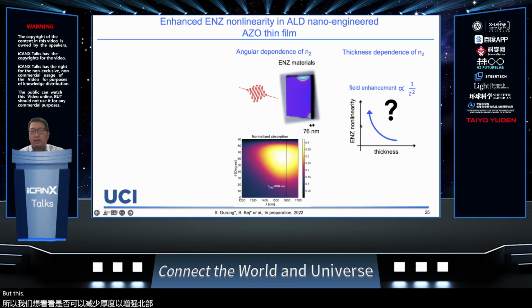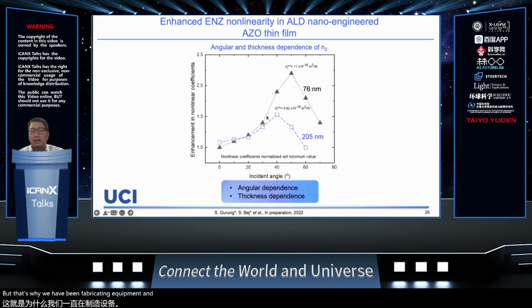That's why we have been fabricating ENZ material with different thicknesses here, 76 and 200 nanometer, and looking at the nonlinear coefficient. You can clearly see that by changing the angle, at a certain angle you have an enhanced nonlinearity. At the same time, with the thinner sample, you also have a certain enhancement because of the enhanced optical field here. So we can clearly see that we have some angle and thickness dependency because of the ENZ mode excitation here.